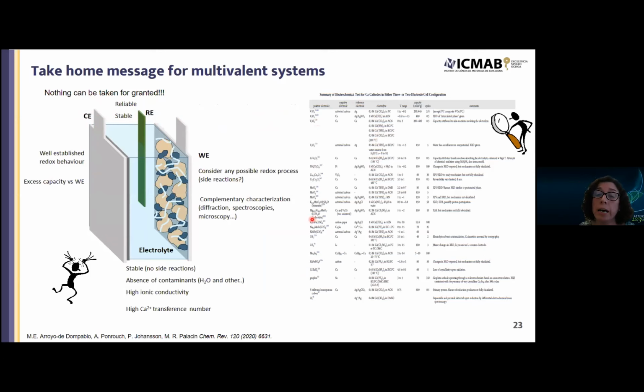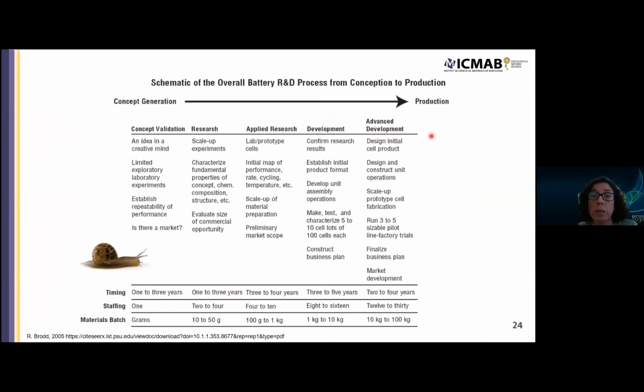And this is a table of all the compounds for which calcium intercalation was reported, so already two years ago. And in some cases, you see that there is only the electrochemical response, so then one has to have a critical view, because some of these interpretations may be biased because of all of these phenomena and side reactions that can take place. So overall, the message is that the development of new battery chemistries can be very slow, especially if there are no preliminary technologies or knowledge which one can import, and this is the case for calcium.